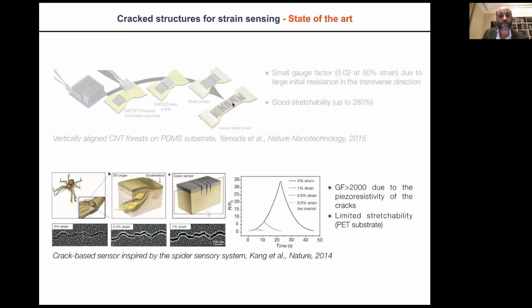You can find also a similar idea in this paper in Nature about cracks in metallic coatings, in which you are using cracks in very thin metallic coatings to introduce piezoresistive sensors. Of course you can get a huge gauge factor around 2000, because the change in resistance of these cracks is going to be very big. But you have a very limited expansion because you are working on a PET substrate, and a PET substrate is going to be relatively limited in terms of mechanisms for stretchability.